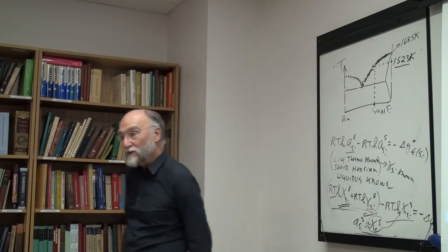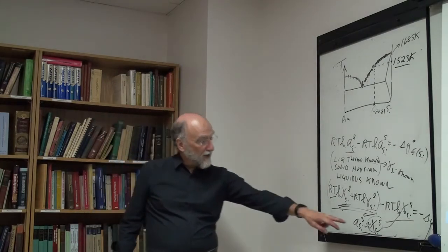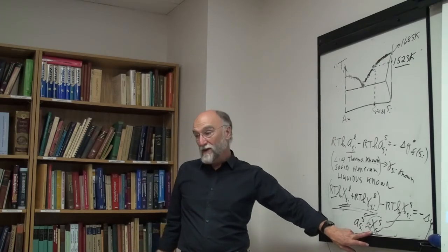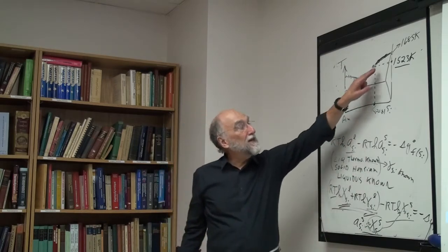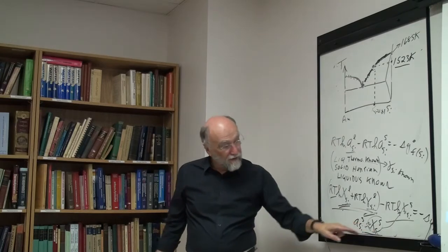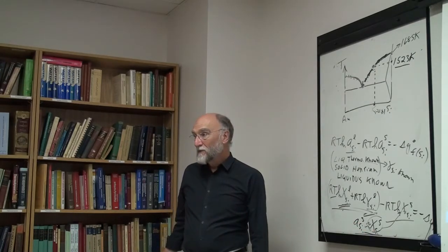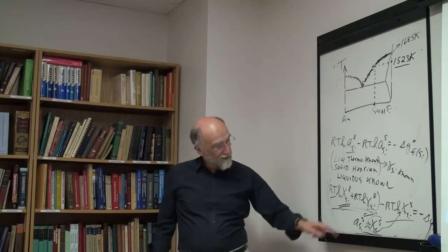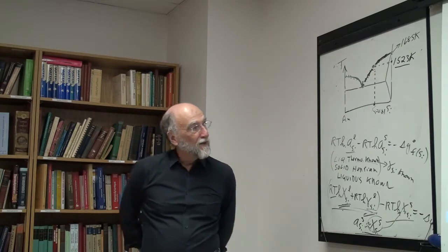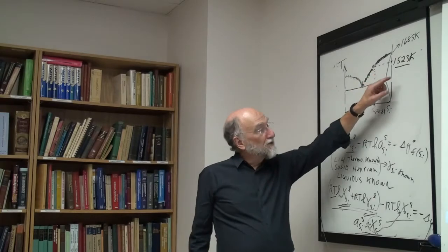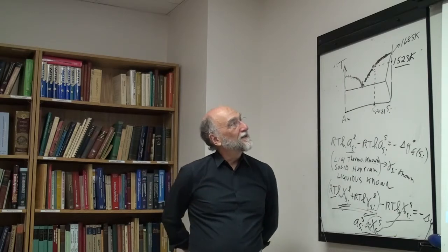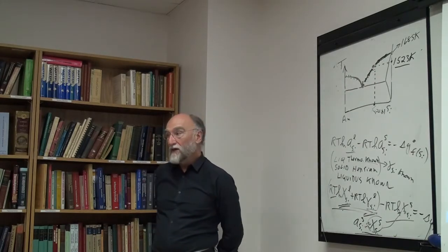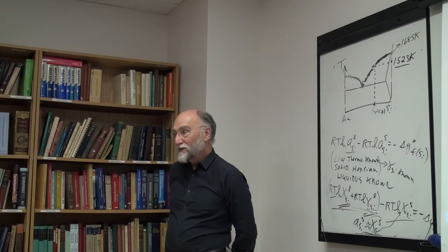Now this is not a really accurate way of doing it, but if I calculate 0.98 here, then that's probably, it could be 1, it could be pure. But if I calculate like 0.85 or something, then clearly it's nowhere near. Okay, so this gives you a rough idea of what's going on. I've done this quite frequently sometimes. So in other words, you can calculate the liquidus assuming no solid solubility, and see how close that comes to the liquidus with solid solubility.